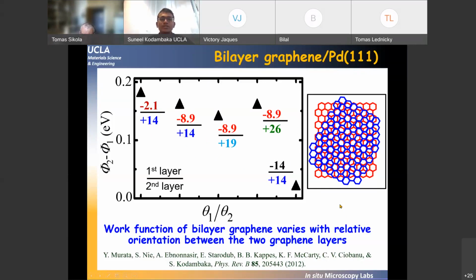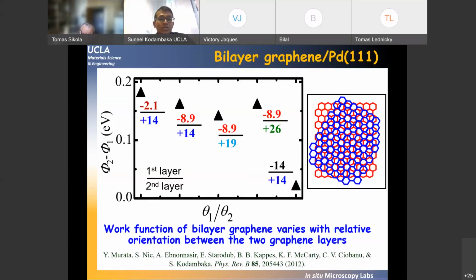So this is important if you plan to make devices, because the relative orientation of the graphene layers affects the device characteristics. Okay, that's the take-home message here. And also, if you're making graphene-metal contacts, the relative orientation of the metal with respect to the graphene layer can also affect the contact resistance.